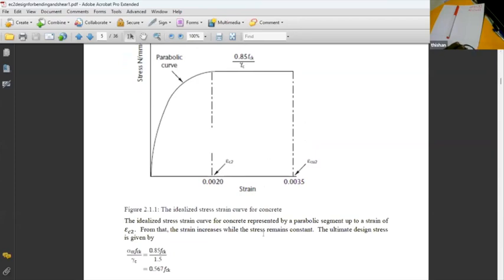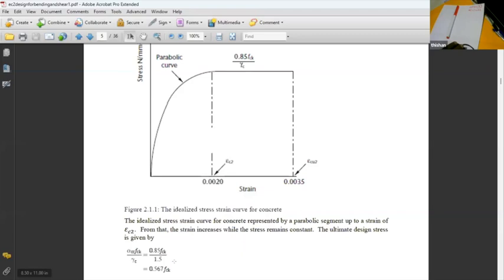And if you want to know the stress that you can allow in concrete, we have to divide it by a partial factor of safety. And the partial factor of safety that we use is 1.5. Now, can somebody tell me why it's 1.5? It is 1.5 because we are supposed to cure concrete once we place it. But many people do not pay enough attention to cure concrete. So what happens? We can't use 0.85 fck because we might be overestimating the actual strength of concrete in the structure. So to allow for that, we use a high factor of safety, not because we are making bad concrete, but because we don't cure adequately.